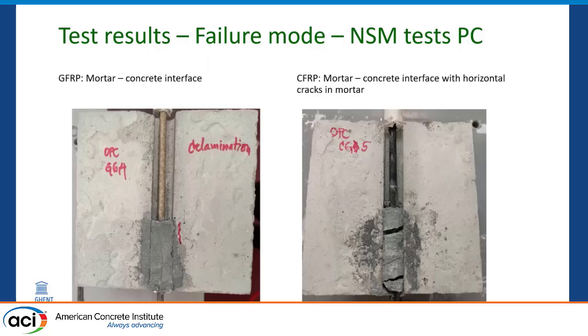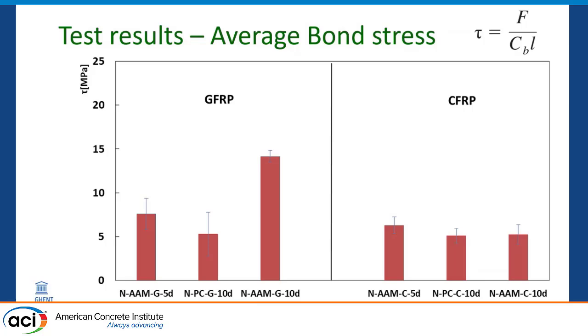There is a different failure mode observed in Portland cement matrix, where for GFRP there was a mortar concrete interface failure on both sides, and for CFRP there was also failure on the mortar concrete interface with horizontal cracks in mortar. Contrary to what is found for pull-out tests, here from 5D to 10D, the average bond stress at maximum load increases for about 50% for alkali-activated materials, and this is for Portland cement, where we see that Portland cement with 10D develops less stress than AAM.